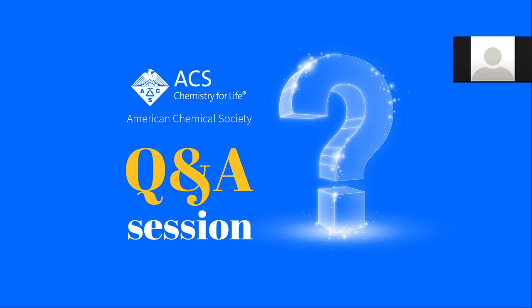He or she wants to know about the molecular dipoles. Is there any direct relationship with the reactivity of the molecule? That's a really, really good question. I'll tell you, early in my career, I was very suspicious of the reports that the dipoles were important. You know, electric fields at interfaces, to me, the charged ions, the lithium and the lithium iodide, the iodide anion, the injected electron, those were what were going to really control the fields. And I thought the dipoles would be smaller. But we have run into cases where the only way we can explain changes in open circuit voltages are to look at the dipole of the dye, and they definitely have an impact.